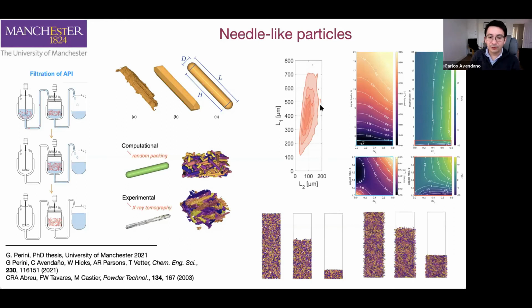For that, we came across this very nice paper by Charles and Federico, which they published for simple cylinders, only monodisperse and binary systems. But we decided to use a similar technique to study the packing of highly polydisperse mixtures of cylinders. And with that, we came up with this phase diagram where in the X direction, what I have is the coefficient of variation of the length of the system. This coefficient of variation, CVL, is telling me how broad